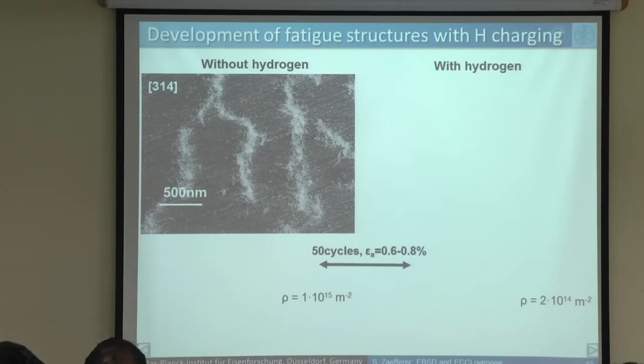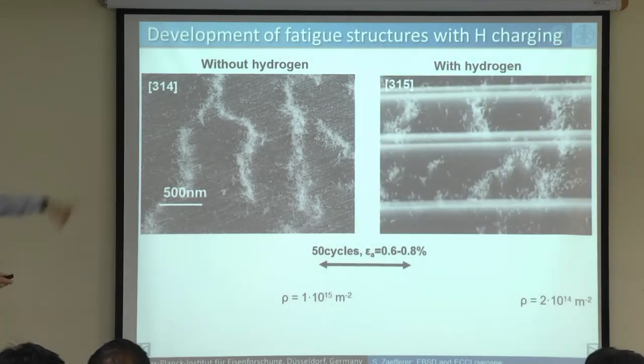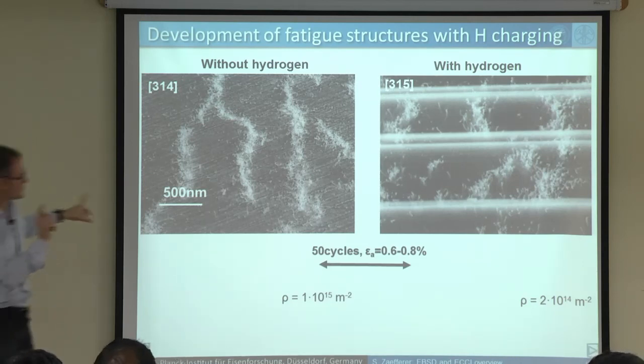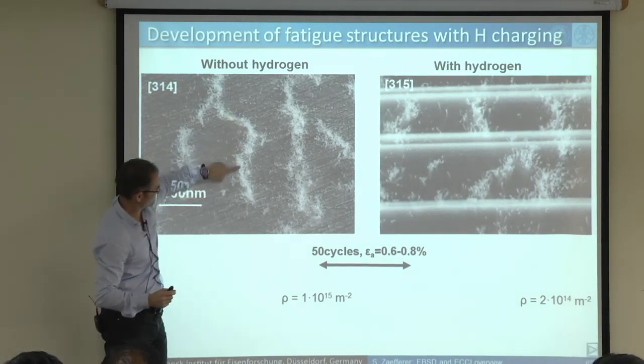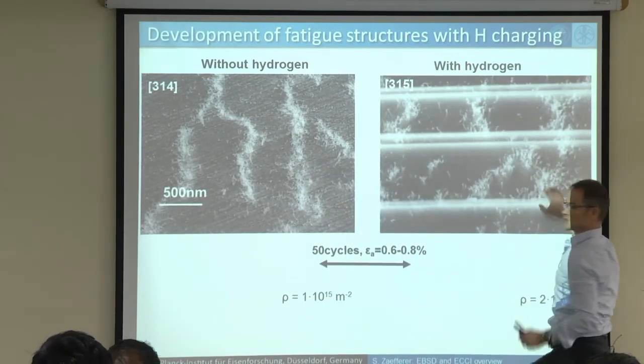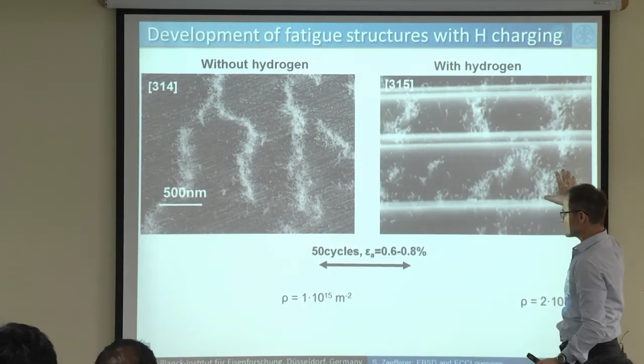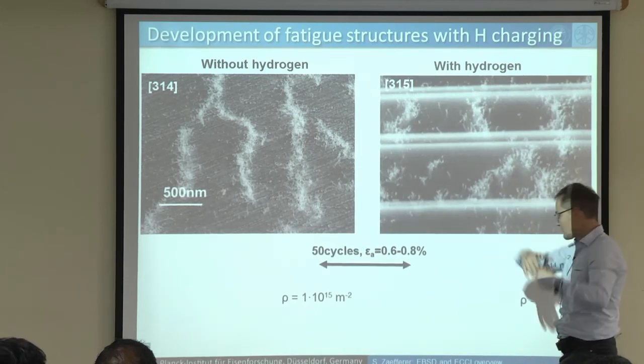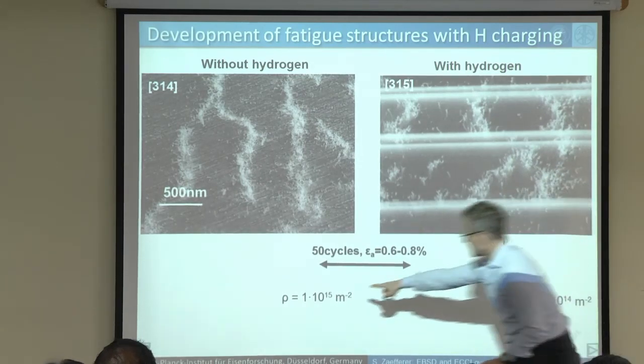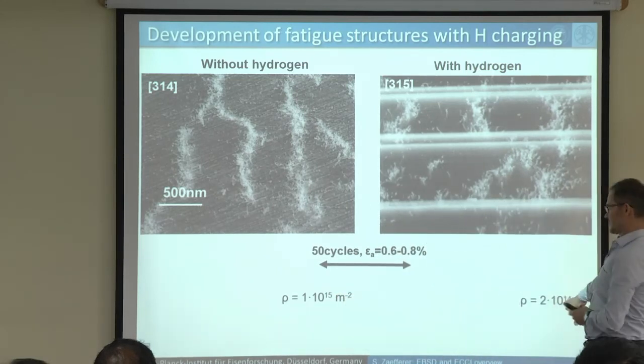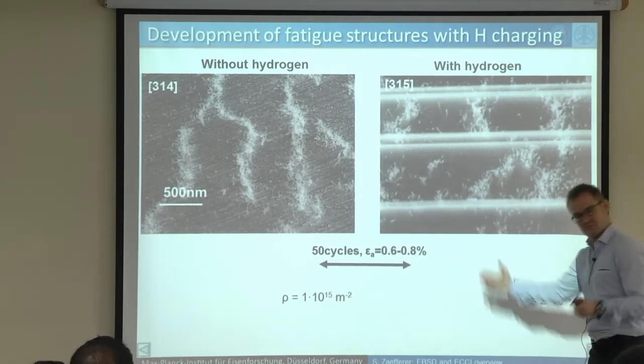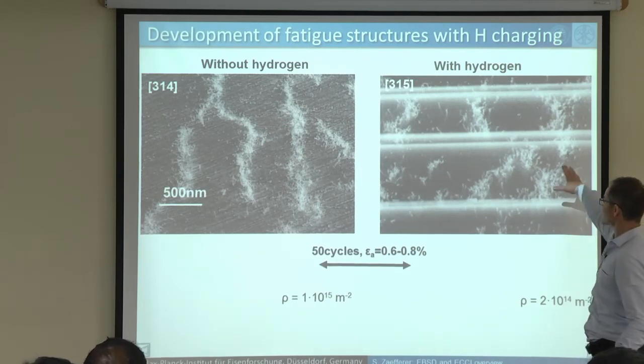If you now look on these structures without hydrogen, you saw it just before, and with hydrogen, same magnification, I think, and more or less the same crystallographic direction, 315, 314, and you see actually these walls here are very dense, very many dislocations squeezed together, while here this is much looser, there's much less dislocations in the walls. Yeah? So with hydrogen we have much less density of dislocations than without. So you see here it's 10 to the 15, and here it's 2 times 10 to the 14, so about 5 times less dislocation density there.